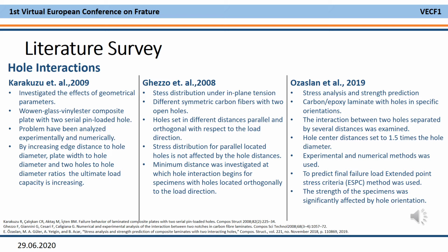The point stress criteria method is a stress-based failure criterion. According to this method, failure occurs when the stress at the characteristic distance away from the hole tip reaches the unnotched plate strength. The point stress criteria method cannot be performed when the critical region is in the highly nonlinear region. Therefore, this method is extended by using failure strength of specimens. The extended method was verified experimentally. The strength of the specimens was significantly affected by the hole orientations.